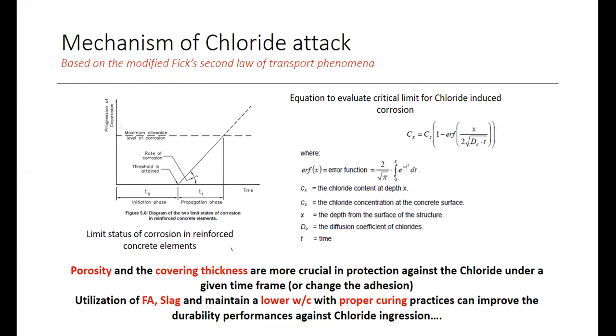If I want to increase the service life of a particular structure, I have to increase the depth from the surface, which means the cover thickness. The diffusion coefficient of chloride has to be reduced, which means I have to make my concrete less porous. Another good thing is to reduce the chloride concentration at the concrete surface, like applying a coating which can reduce the permeability of the concrete, or reduce water penetration by applying some nanofilm or different techniques. With those techniques, we can address the basic governing factors for chloride penetration or chloride-induced corrosion.